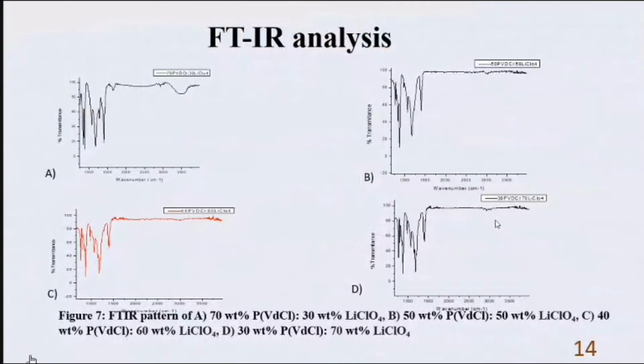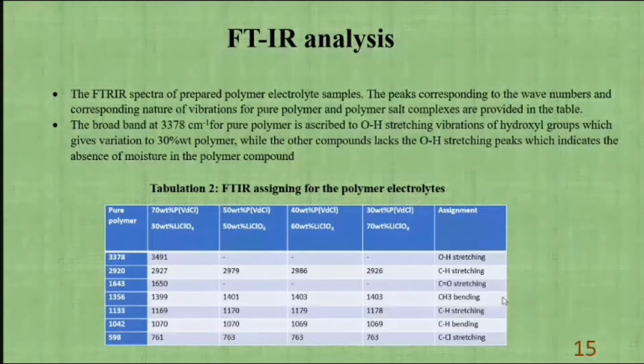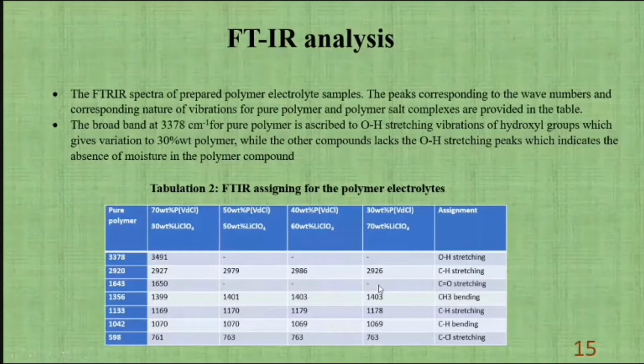And from the FTIR analysis, we can see that this is the characteristic peak for water. It's also called an OH stretching peak. On increasing the doping material, lithium perchlorate salt, the moisture of the membrane disappears and it becomes suitable for the battery membrane. Also the complex formation between the carbonyl group and the salt has been confirmed, as shown in the figure. The carbonyl stretching frequency has disappeared, which means that a complex is formed between the polymer and the salt.